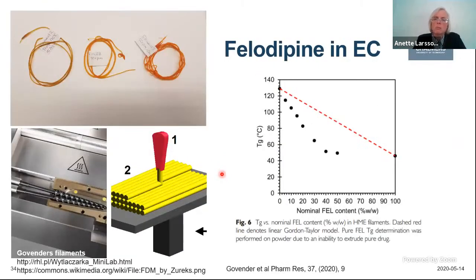So here is an example where we have ethyl cellulose, into which we have mixed a drug called felodipine, and here are filaments from work in our group. And you can see that the Tg for these filaments decreases, and this follows the Gordon-Taylor model, so it's not behaving ideally. And today, very little is known about why this felodipine interacts as it does with the EC. And we could also take these filaments and print them and make tablets and check the drug release rate, which is at least possible to do.